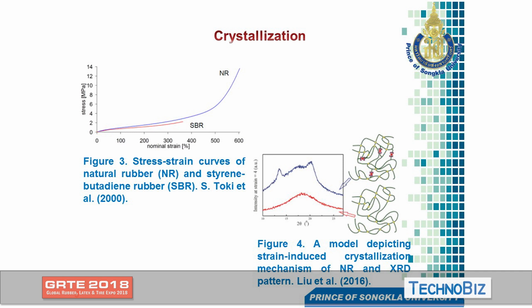Another method to check the strain-induced crystallization is through XRD, or X-ray diffraction. Here are two different patterns of natural rubber. The first one, the red line, is the normal state, the unstretched rubber. Nothing happened here, which means there are only amorphous regions. Once we apply a strain or stretching, it gives two distinct crystal peaks. That means crystallization occurred in the natural rubber. But this only happens after being stretched at a certain strain, at higher deformation.